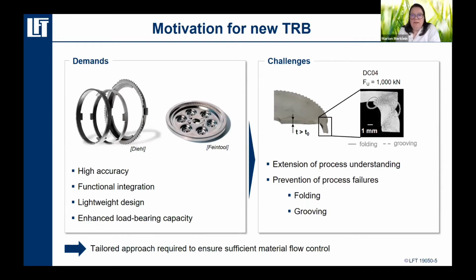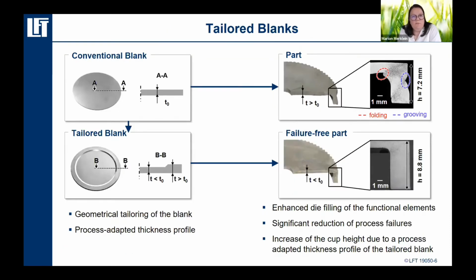And so what you can see on the right as the challenge is that we said it's really important to have a first trial to determine which problems may occur. And as you can see here, folding, grooving, these are the typical problems because of the missing stiffness of the component, for example, of a material backflow that is not wanted. And so our idea was, why not use the idea Rainer Kopp had many years before, and enhance this idea to come to a tailored approach to ensure a sufficient and improved material flow control in such forming processes. And so what we did was, we said, besides such tailor rolled blanks with a linear connection between two areas, it has to be possible to also have circular tailor rolled blanks.